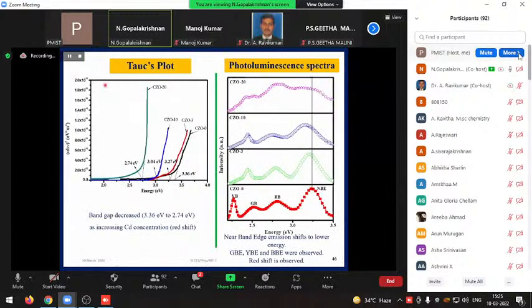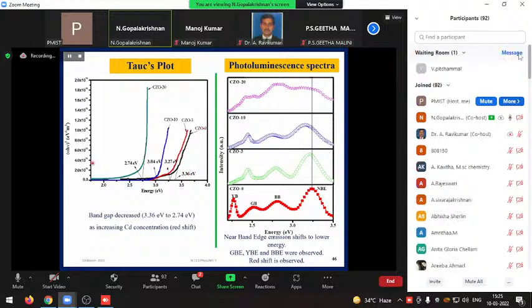Then we also made the Tauc plot. As I said, this is pure zinc oxide, and upon doping with cadmium, the band gap decreases. Then we found the different defect levels. We measured the photoluminescence of the grown films and got the yellow band, green band and blue band. We also studied the effect of doping on these different defect levels. These may be attributed to oxygen vacancies and zinc interstitials. How upon doping these defects are suppressed, or how the intensity changes, was always studied.